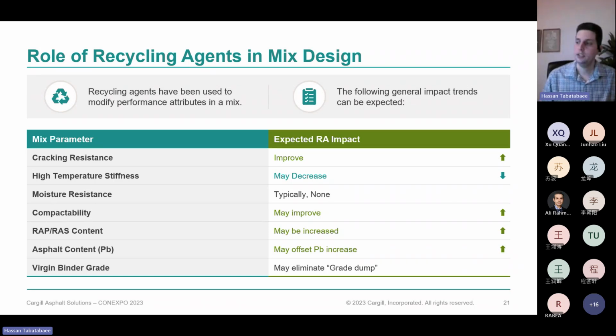You may not need to increase the asphalt binder content as much as sometimes people do when they're using recycled asphalt. And it also can help eliminate what is sometimes called a grade dump, which in other words means using a softer grade than usual in an asphalt mix because you're using recycled material.